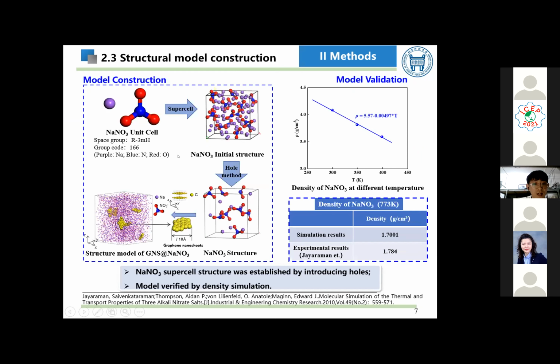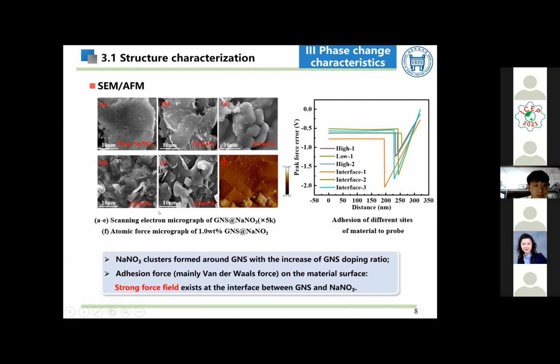As you can see, sodium nitrate supercell structure was established by introducing holes, and the reliability was verified by comparing the simulation results and experimental results of the density at 773 Kelvin. GNS was randomly introduced into the sodium nitrate structure model to simulate the random distribution of the nanoparticles.